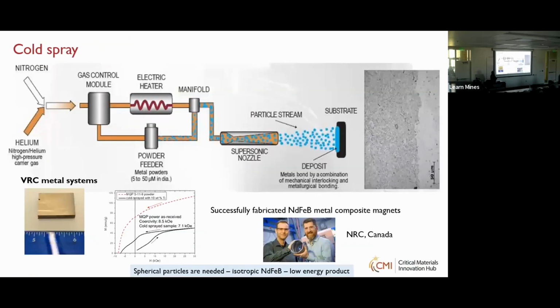So cold spray is another additive manufacturing technique people use for aerospace, like all the planes, if there are cracks in the plane, they use the cold spray to really seal all the joints. So it's like high speed with a nitrogen helium gas, you can take the powders and go through this and deposit at high speed. And NRC in Canada actually made some work on that. And we also worked with United Technologies a very long time back on this.